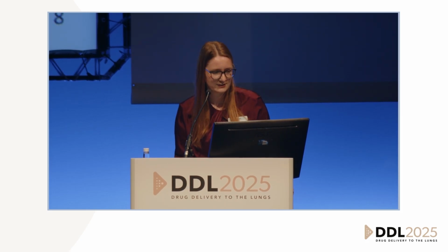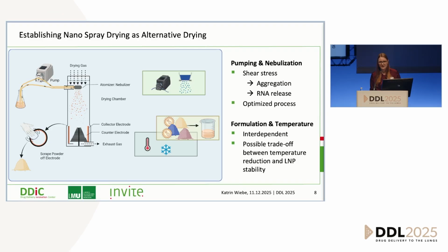I know that usually for spray drying, outlet temperature is the interesting one. However, in this case, I hope that you can see it here actually. You see that the atomizer is hanging really inside of the airflow. And because we're nebulizing so slow, the feed will sit in the inlet temperature pre-nebulization for a bit of time. So we also have to keep in mind that even the inlet temperature needs to be very, very low here, and not only the outlet temperature is interesting.